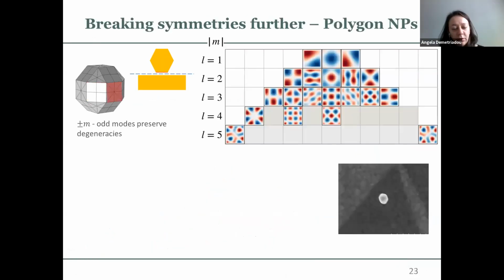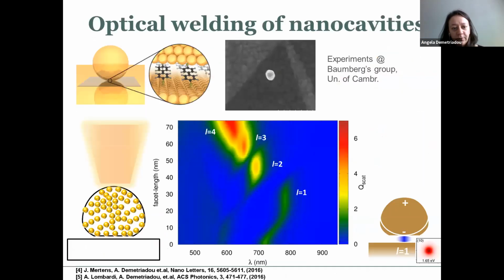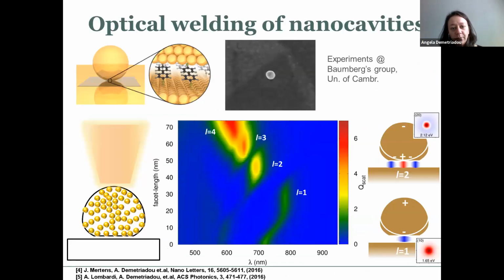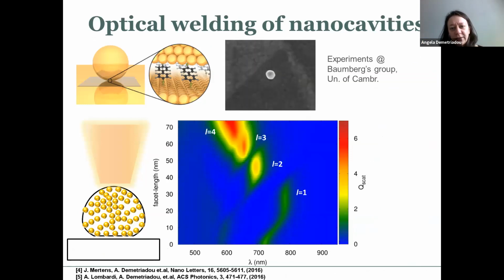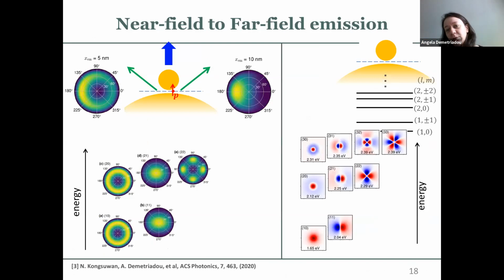I think you're referring probably to this one here, right? So the local density of states, we usually measure it as the field enhancement in the near field. However, this is how each one of these modes separately emits into the far field. So what we did was a mode decomposition, like an eigenfrequency solution that was done numerically, and then obtained the fields around the structure and then exported them to the far field for each mode separately here. But the local density of states refers to how all this superposition of modes couples into the quantum emitter. I'm not sure if I'm clear.